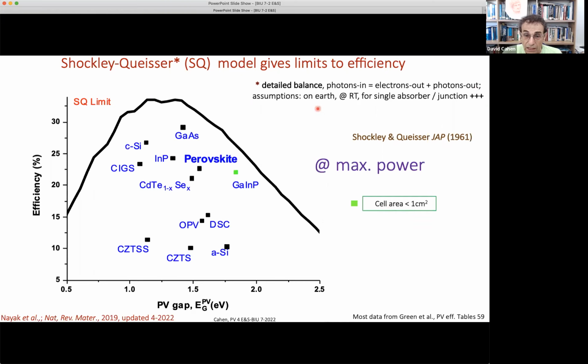The assumptions are that this happens on Earth at room temperature for a single absorber, single junction. And I'll come back to those assumptions. So here is the theoretical limit with a modern day solar spectrum that we know. And here are the best performing solar cells where all are 1 centimeter square except gallium indium phosphide, because it has not been made in such area. And you see that we're not doing that fantastic. There's quite a bit of difference between the theoretical maximum and where we are.